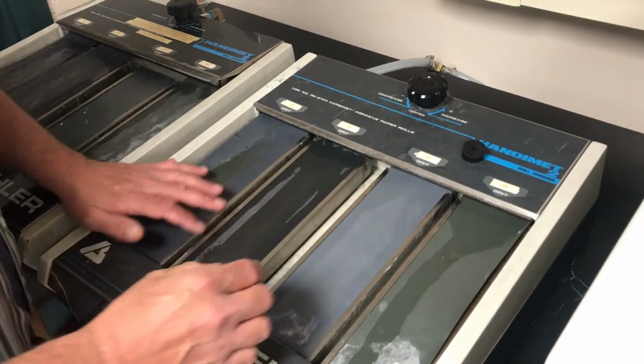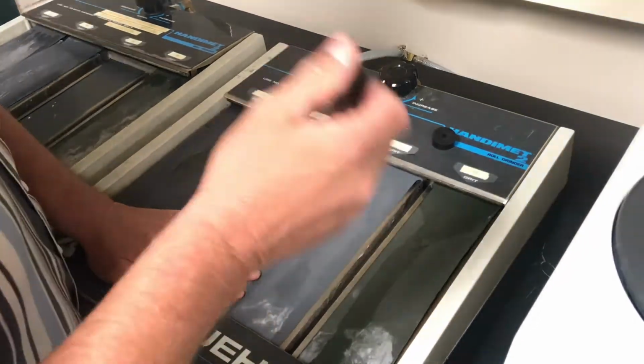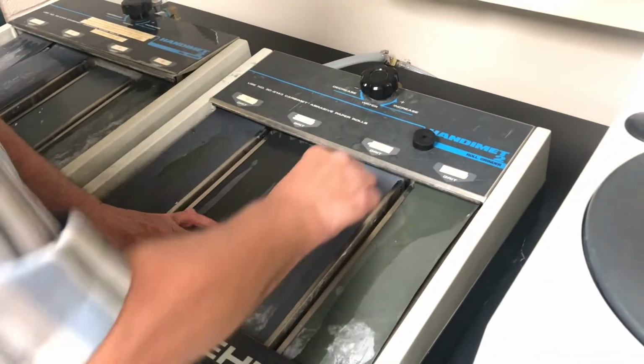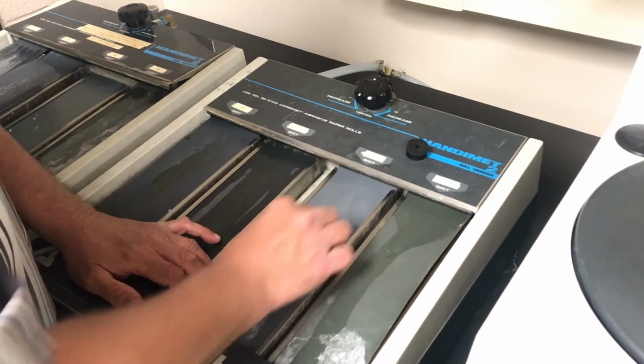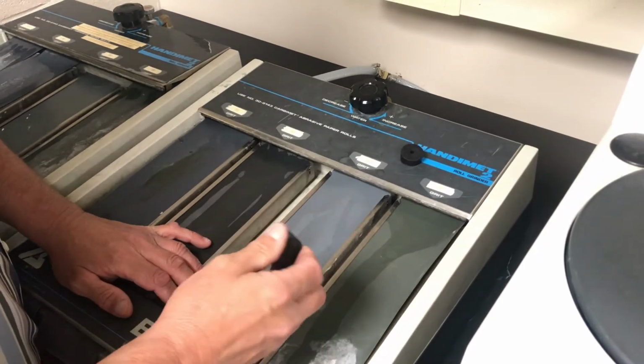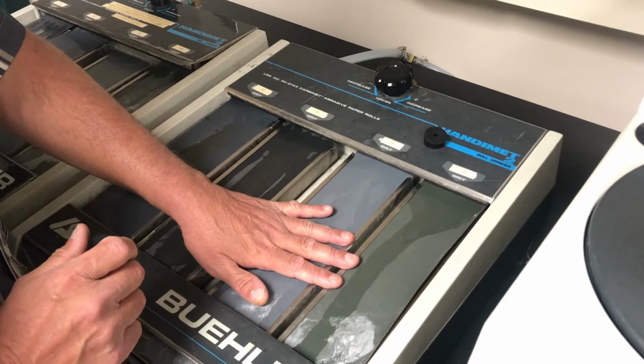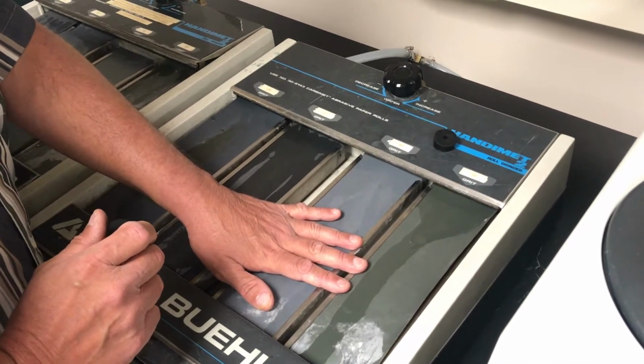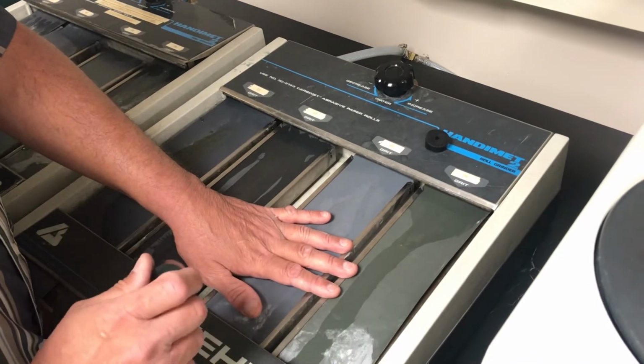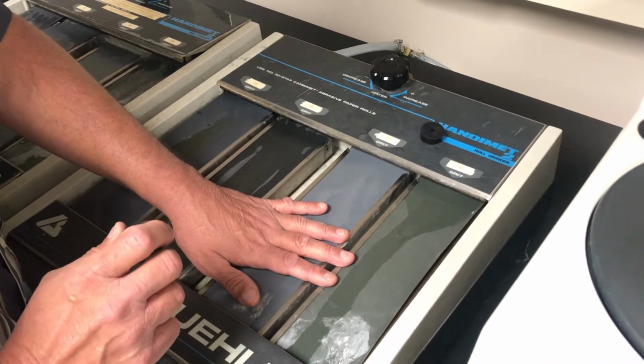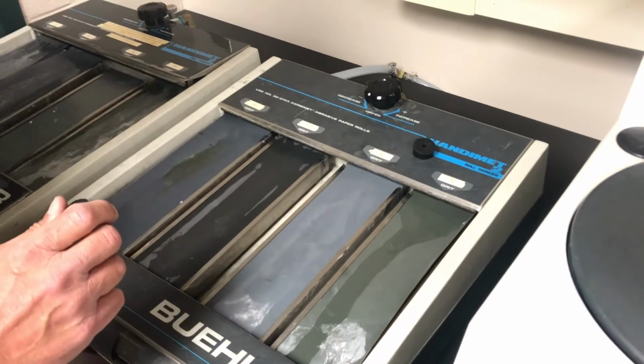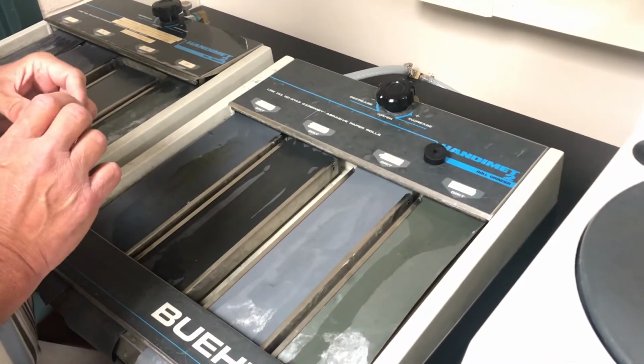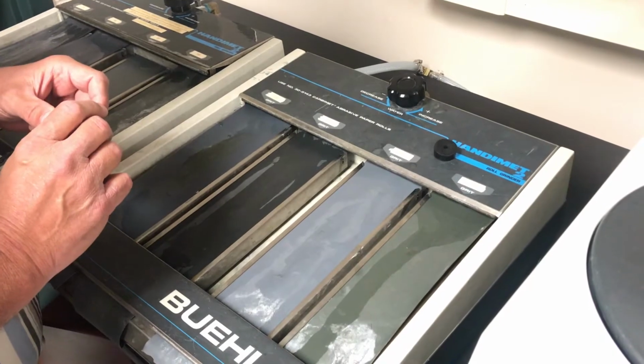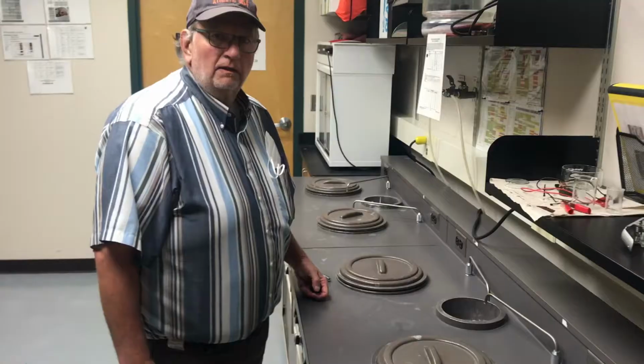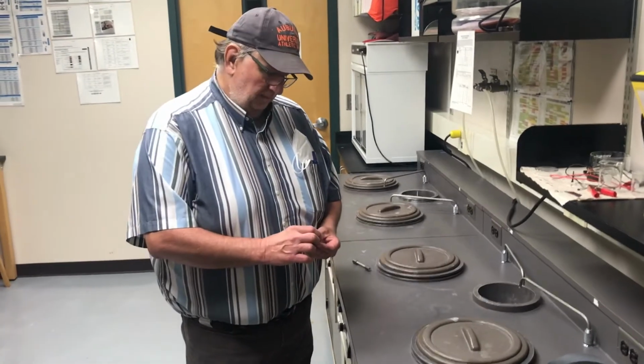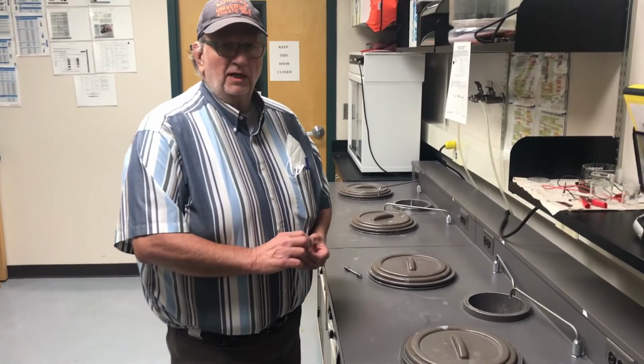Okay? Go on to 600, do the same thing. Rotate your sample 90 degrees. Again, 20 strokes or so in one direction, not back and forth, and you should end up with a pretty nice finish after 1000 grit. That'll take you to a 1000 grit finish, and you should see at this point a pretty nice shiny surface. Not a mirror surface, but a pretty nice surface. Fine scratches all in one direction. Okay? That's it. So the next step is what we call, I guess, a medium grade polish.